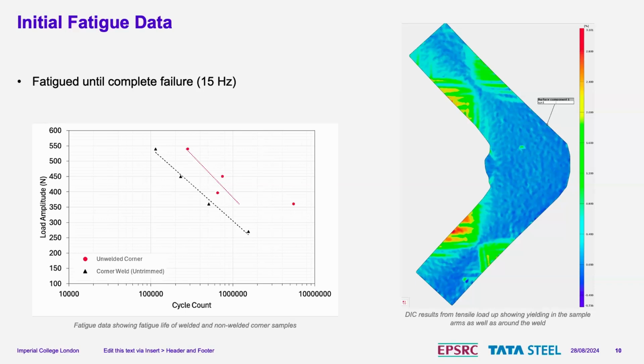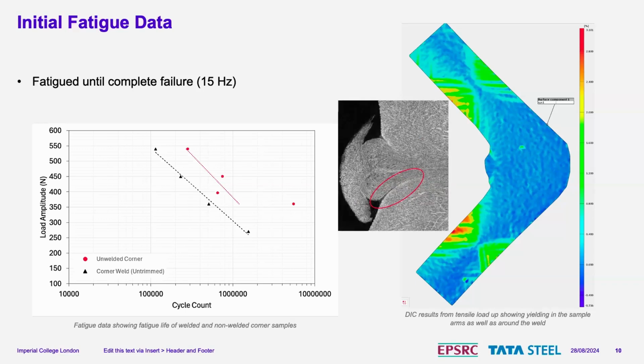And if I go on, this is theorized to be because of these features. When we've had that squeeze, we get a lot of oxides in here, and we don't get full fusion of the material. And so the hope is, if you take off the internal weld bead, you'll get a nice smooth surface, and so we shouldn't get that squeeze. Some of the future work is to test these, the trimmed ones, and hopefully it'll restore the fatigue life back up to where it is for the unwelded sample.